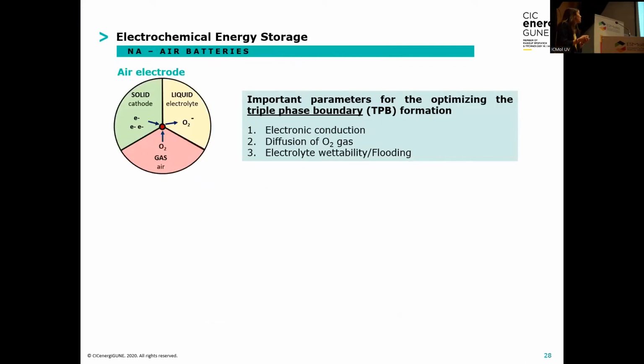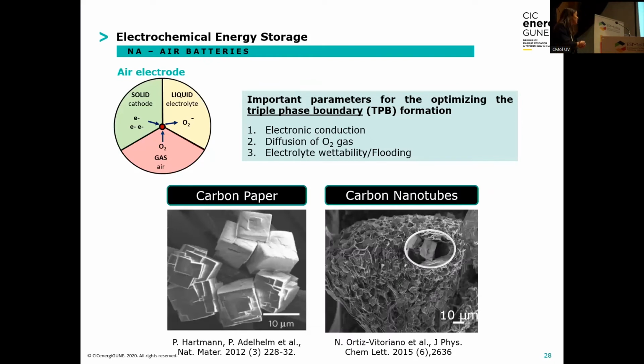So for that, the so-called triple phase boundary is really important. This is where the reaction is happening at the air electrode, with the solid, which is the cathode, the liquid, and the gas. And here we have been working with different carbon materials. The first paper was from 2012 from a German group, where they used carbon paper. And then later we were also using carbon nanotubes. As you can see here, you can better accommodate all the discharge products, so this one had higher discharge capacity.